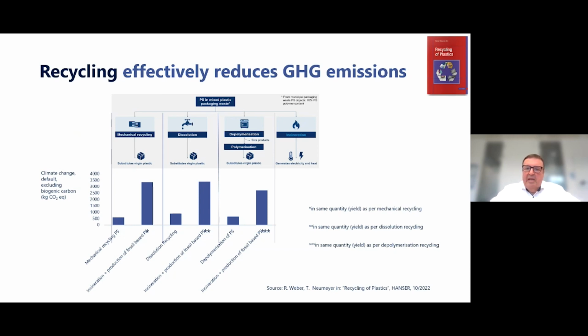Do you see any difference? In a nutshell, we can say yes, there is a slight difference, but there is also an overarching scheme. If you do the life cycle analysis according to ISO standards and define boundary conditions, mechanical recycling of polystyrene in comparison to dissolution recycling and depolymerization, then you see that the bar pairs consist of the fossil-based solution, which is always the higher right bar, and the recycling solution is the lower left bar.